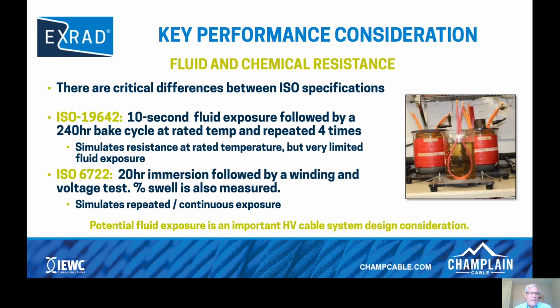Now, in the past, ISO 6722 used an immersion test, as do SAE standards. And I like these tests because they really simulate what happens when you have a drip of oil on the cable. Unlike the 10-second dip and then bake, that's really not showing a real-life situation where you have a constant drip of oil. And that's what the ISO 6722 test does. It's a 20-hour immersion test followed by a winding and voltage test where you measure percent swell.